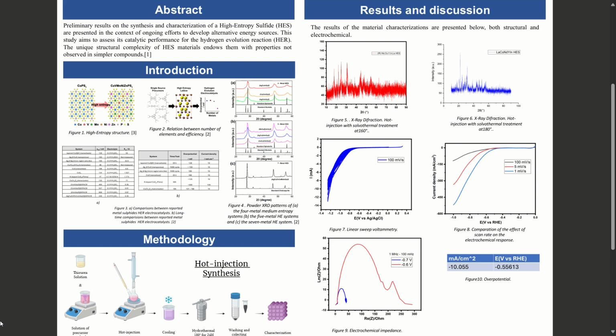Interestingly, the material showed higher current density at slower scan rates. This behavior suggests that the intrinsic catalytic activity is strong, and that slower scans allow for better utilization of the active sites. Three, stability results. A stability test showed that the material was able to maintain its catalytic activity during extended electrochemical cycling. While more long-term tests are needed, the preliminary results are encouraging, showing that the catalyst does not degrade significantly under reaction conditions.